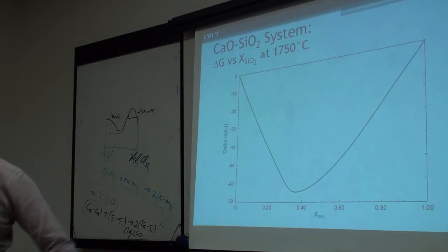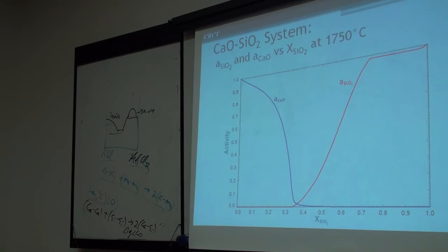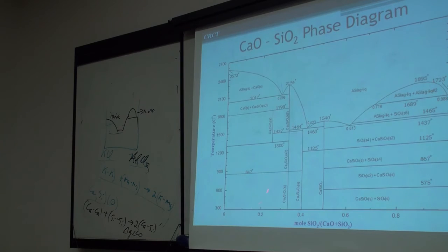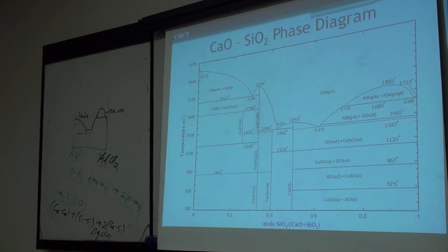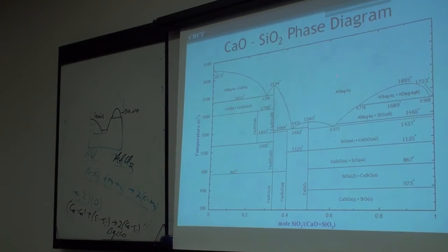So what you end up with is these miscibility gaps. And there's your phase diagram. Here's your calcium oxide silica phase diagram, and you have this miscibility gap. Over here it's ionic up to 33%. Then it starts to become more polymerized, but it still is more or less ionic. But over on this side, it's quite covalent. So you don't want to mix, so you're going to get a positive deviation, which tends to give you two-phase miscibility on that side. Very much like KCl, AlCl3.